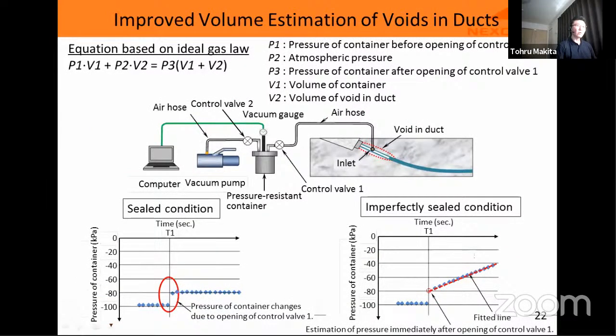To make sure that all the voids are fully filled with repair grout, instead of improving void detection methods, the method to estimate void volume in the duct was improved. This method uses a vacuum pump, and the volume of voids is estimated by using a simple equation based on the ideal gas law. So even if the system is not sealed and there is leakage of air, the pressure P3 of the container immediately after opening of control valve 1 is estimated from a fitted line of measured pressure of the container, and by using this equation, V2, the volume of void, is calculated.